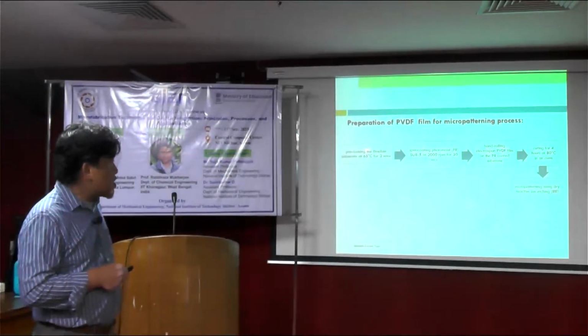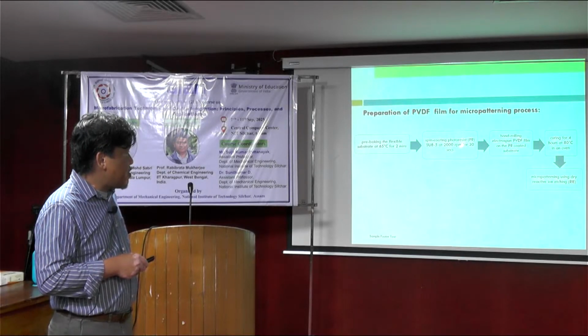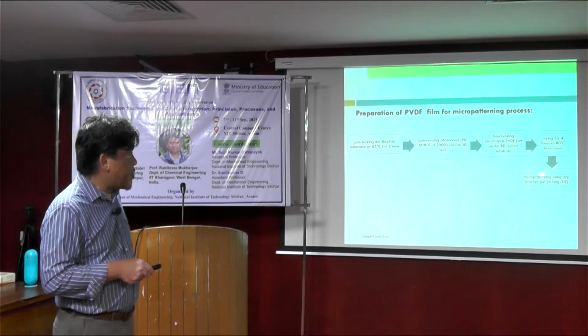So the process in details, it involves, this is quite normal in terms of micro device design, to go through this kind of process: pre-baking of flexible substrate at 65 degrees Celsius for 2 minutes, then spin coat photoresist, as I mentioned before. We will look into photoresist properties later on. Then hand rolling electrospun PVDF on the substrate, curing at 80 degrees Celsius, and micro-patterning using reactive ion etching.